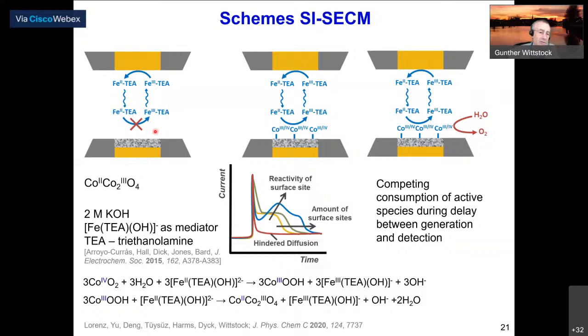And in this case, we need to titrate the oxidation states of this cobalt oxide by a mediator which is compatible with alkaline solution. We used the iron triethanolamine complex. That is a suggestion from the Bard group for alkaline media. And then again, we titrate the surface, but now we have different oxidation states which this material can assume, and here are some tentative reaction equations given which show these valency changes for different cobalt sites in that spinel oxide.